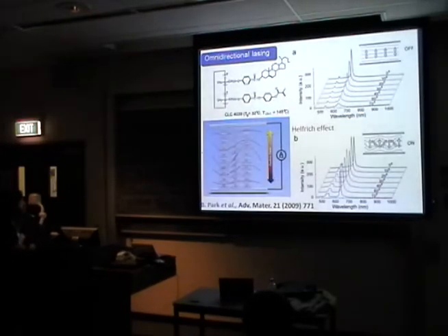By changing the field, we can achieve right-handed polarization, TM modes, TE modes, or left-handed polarized light. The degree of polarization is quite good if you look at this small peak. So we can apply this method to a conventional liquid crystal laser too.